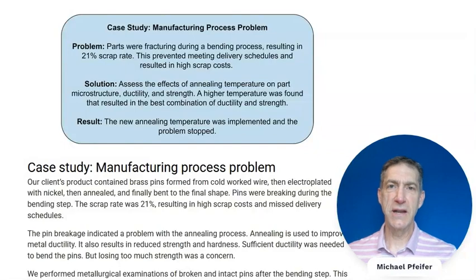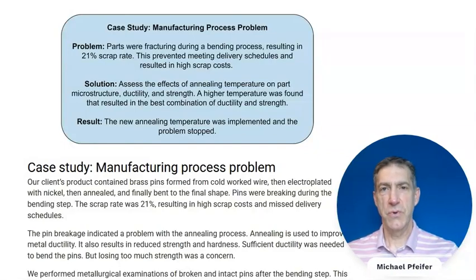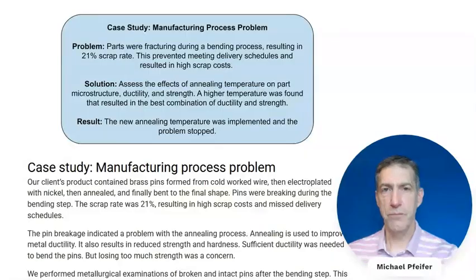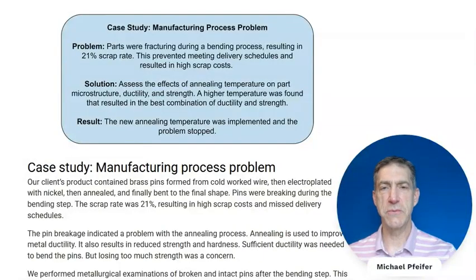So the pin breakage indicated that there was a problem with the annealing process. So we received samples of the cold work metal and the pins: the broken pins after annealing and bending, and the intact pins after bending. And what we saw is that the broken pins were not annealing. Their hardness was the same as the cold work pins, whereas the unbroken pins had a slight decrease in hardness, though they had a partial recrystallization, or they were partially annealed. So we saw there was a problem with the annealing temperature. Sometimes the temperature was too low, and that was resulting in the pins not annealing at all, and there was no reduction in the strength and increase in the ductility needed to be able to bend the pins without breaking them.